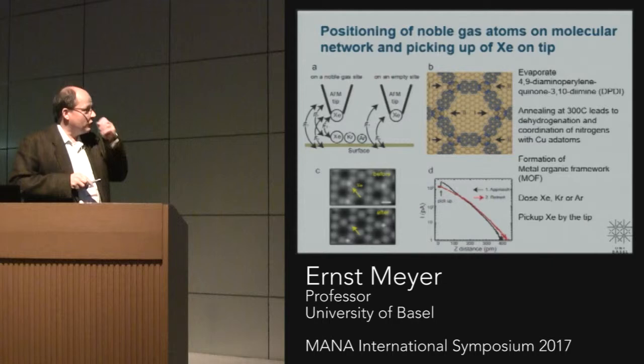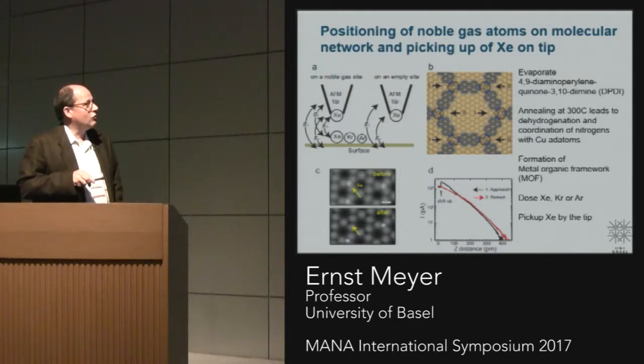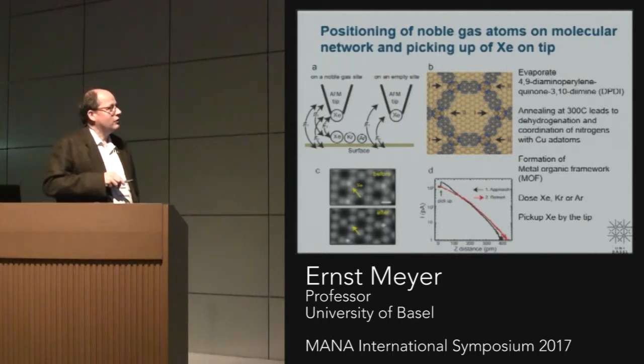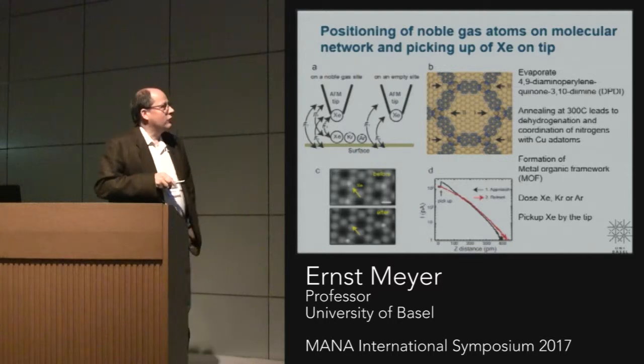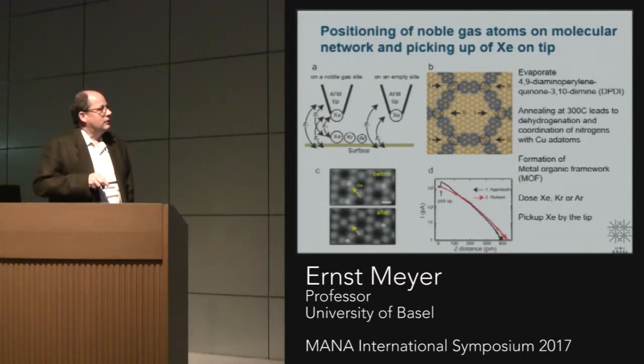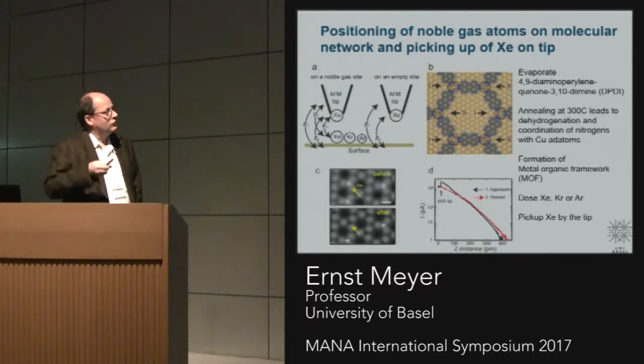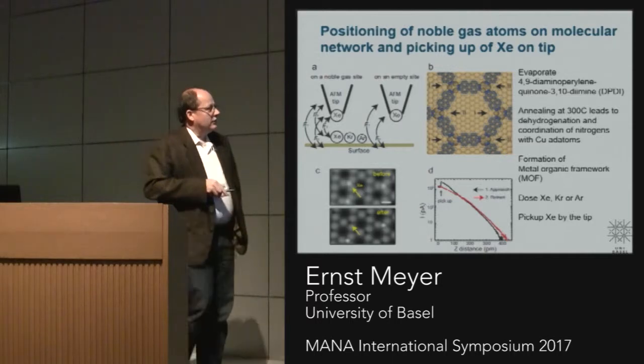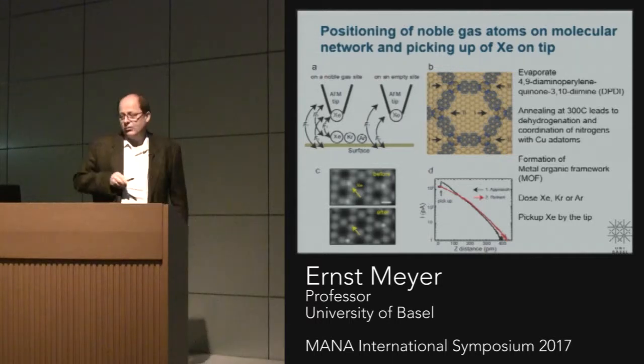I mean, we won't go into too much detail, but essentially you first have to grow this molecular network, a metallo-organic framework, and then you put the xenon atoms here, and then finally you have the xenon on the tip and measure the interaction. So that's sort of the sequence.